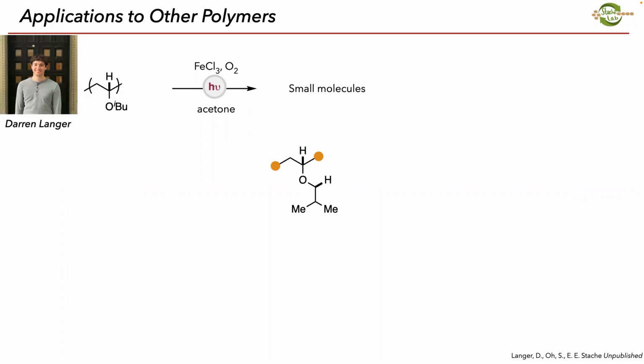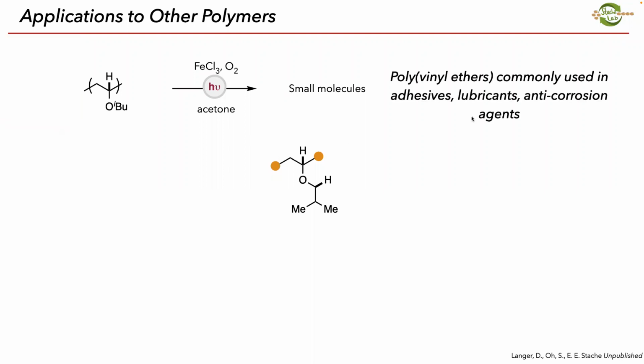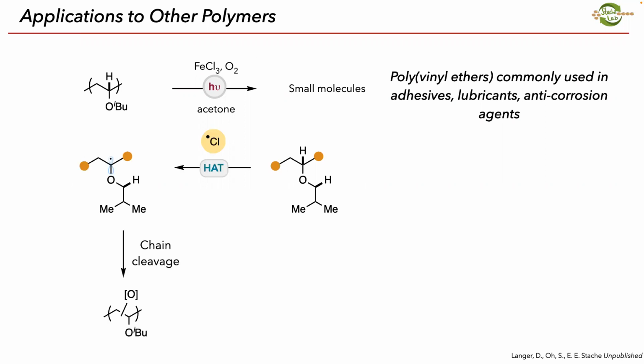This is not restricted to just polystyrene. We can also use this on other commercial polymers. And so Darren is an undergraduate in my lab. He's a third-year undergraduate. And so he's working on vinyl ether degradation, which is shown here as this repeat unit. So polyvinyl ethers are commonly used in adhesives. And so if you have your little Post-it notes, there's probably some polyvinyl ethers in those, lubricants, anti-corrosion agents, things like that. And in this case, he subjected this to similar conditions that Sewon was using for polystyrene degradation.